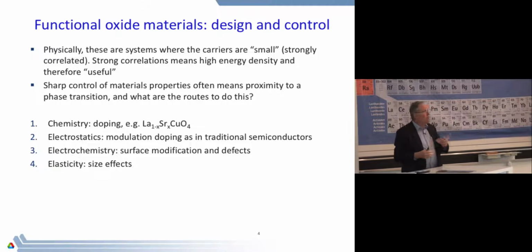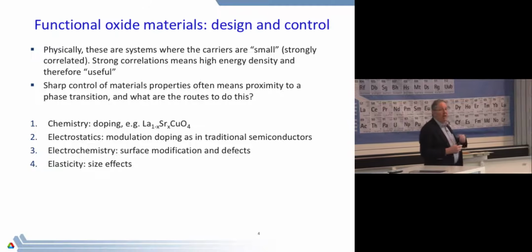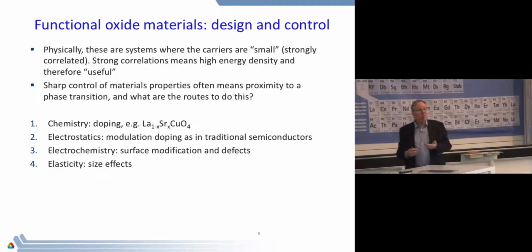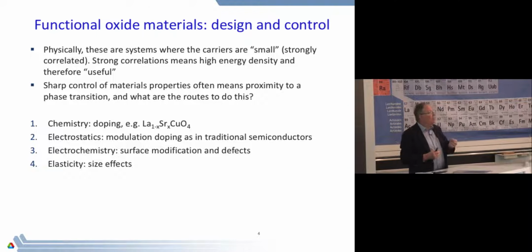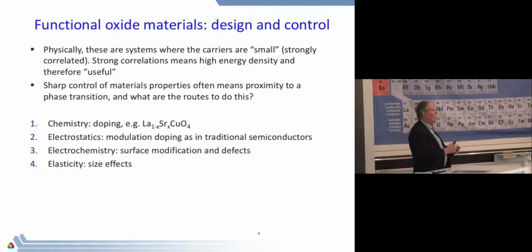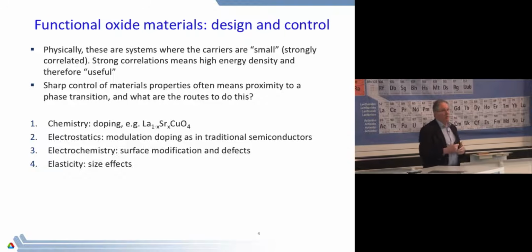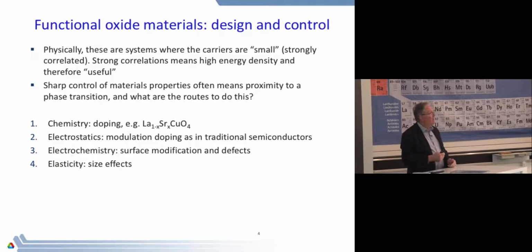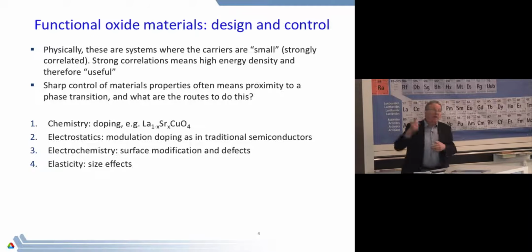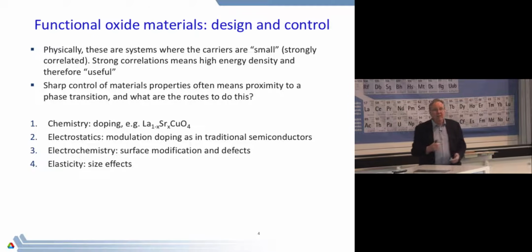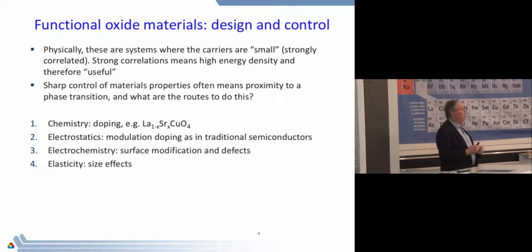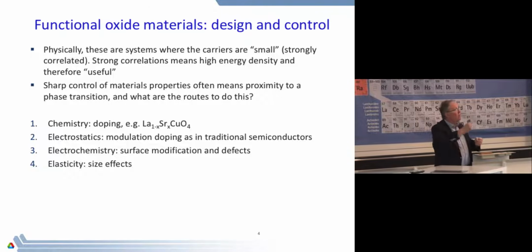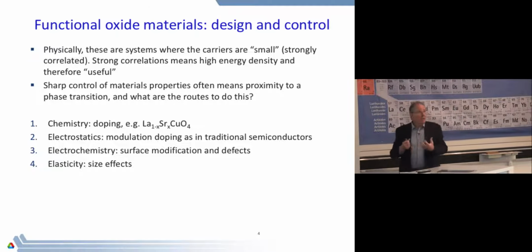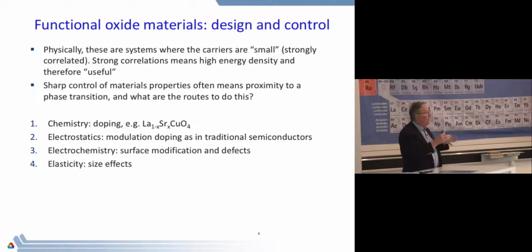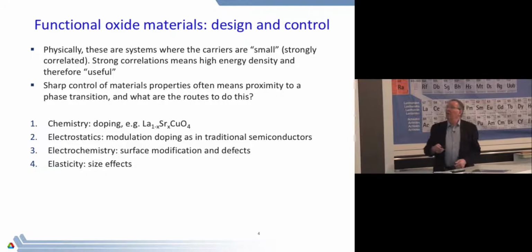And the reason is that in a material where the dielectric constant is 10 and the effective mass is 1/10, the binding energy of a charge to a positive charge produces a hydrogenic radius which is quite big. So you don't put many electrons into silicon. The nice thing about these materials is that the dielectric constant is of order 1, the mass is of order 1, the binding energy is very strong, so you can pile huge amounts of charge in and out of this stuff. But those electrons see each other because they're piled up very tightly, and that produces strong correlation physics.